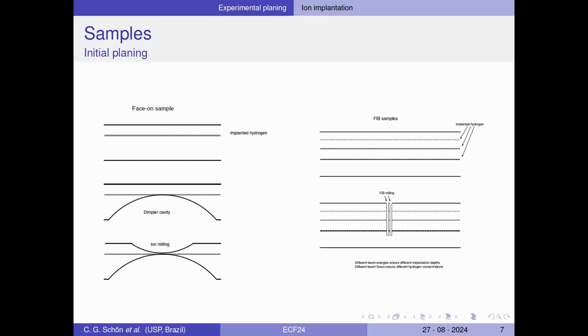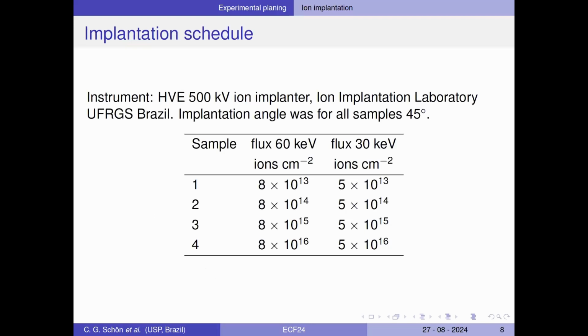The original idea was to do two kinds of samples. The first one was what we call the face-on sample. We would implant hydrogen and then thin from both sides, one with the dimpler, the second one with ion milling, so that we could observe the region affected by hydrogen. The other idea was to implant hydrogen at different depths with different quantities and then produce a FIB sample to look at very different hydrogen levels. This is the first experiment we did, and I must say to you that we are at the beginning in this area. So we have only the first experiments to report.